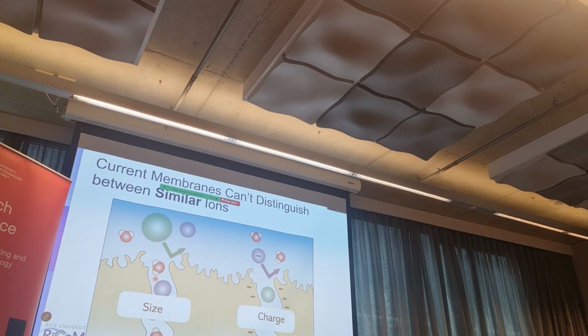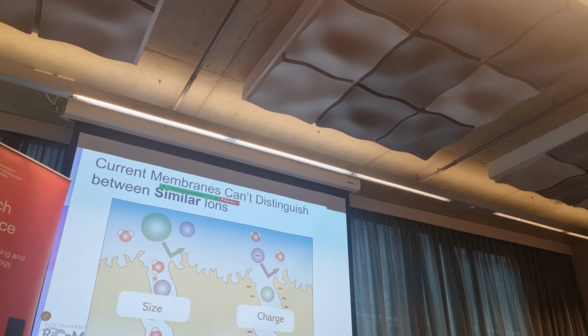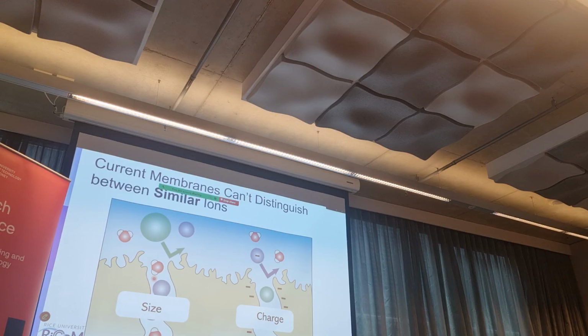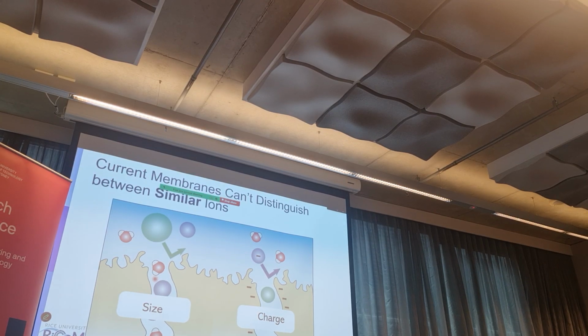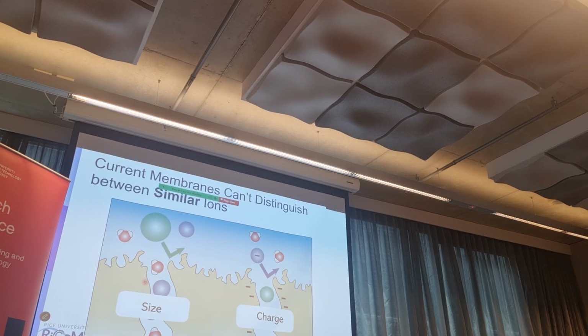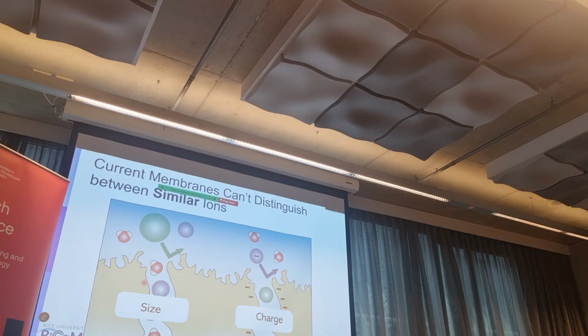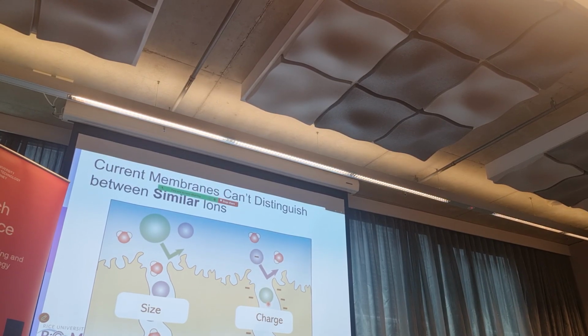The problem with current membranes - most of the membranes you see in the literature, the ones we really use, are polymeric membranes. And polymeric membranes cannot distinguish between ions of similar size and charge, because the mechanism is by size exclusion, but the polymeric membrane has a very wide distribution of pore size, and also by charge. Simply by charge, by Donnan exclusion, it's not enough.